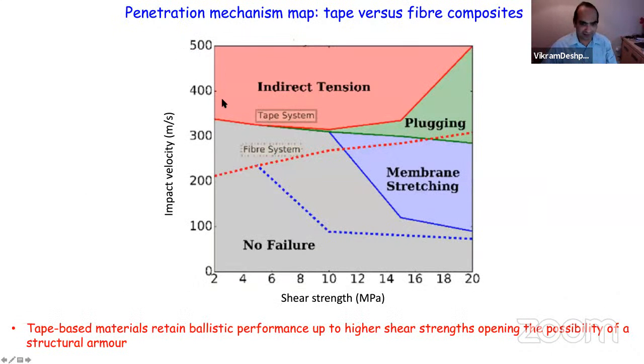And this is a sort of a simulation map which is showing what will happen if you make a tape-based composite. So the dotted line is showing the mechanism map for a fiber-based composite. This is the tape-based composite. So it's telling you that not only will you increase the ballistic limit if you go from fibers to tapes, but you'll also increase the shear strength at which the optimum performance is reached. And this is important, because in principle, if you have a high shear strength, then you can start thinking of this as a structure, because right now these composites with 5 and 2 megapascal shear strengths are not structures. They are sort of parasitic when you use them.